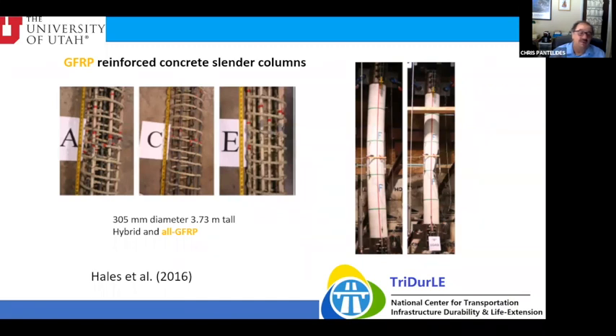The main reason we use the fiberglass spiral is because we believe it protects the vertical steel from corrosion. Because corrosion, as you know, will have to come from the outside, right? And my belief is that if you have the fiberglass protecting the vertical steel, it's much harder to get the chlorides to attack it. You're actually creating an extra barrier for those chlorides to go in. And even if they go in and attack the vertical steel, the byproduct is probably not going to push out the concrete, the volume expansion that you normally see in all steel reinforced columns.